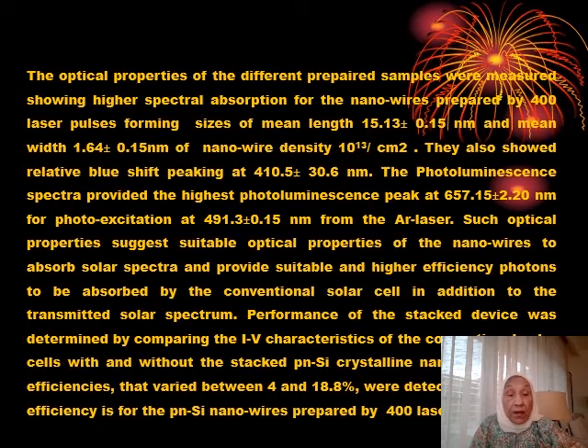The photoluminescence spectra provided the highest photoluminescence peak at 657.15 plus or minus 2.2 nanometer for photo excitation at 491.3 plus or minus 0.15 nanometer from the argon laser. Such optical properties suggested suitable optical properties of the nanowires to absorb solar spectra that is not utilized by the conventional solar cell and provide suitable and higher efficiency photons to be absorbed by the conventional solar cell, in addition to the transmitted solar spectrum.